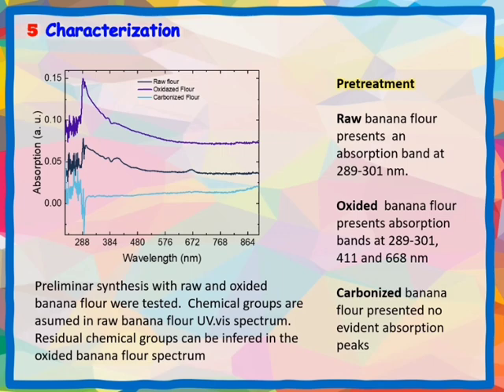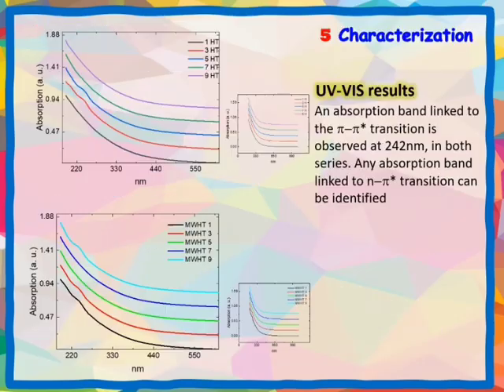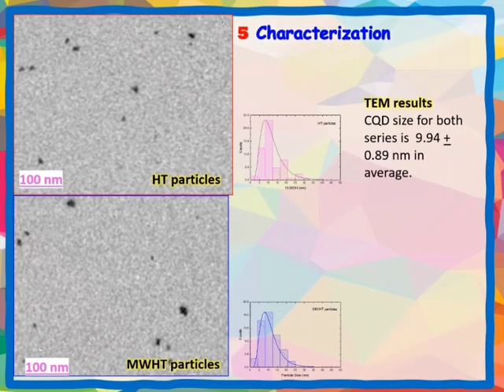These are the absorption spectra of both synthesis series. An absorption band is observed at 242 nanometers. This band is linked to the excited pi-to-pi transition of carbon bonds. No band is observed linked to the excited n-to-pi transition, which is linked to the transition of other orbitals to the excited pi orbital. The TEM images show particles with an average size of 9.94 plus or minus 0.89 nanometers. Their shape is irregular.